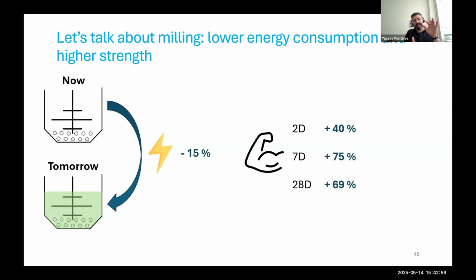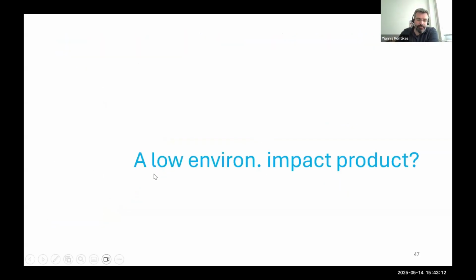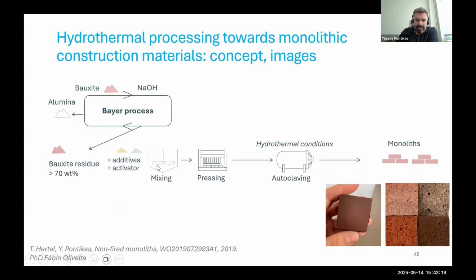So instead of then actually sending the dry powders, you can send the slurry, and you say in that slurry, add your aggregates and 5% cement, cast, because it's still castable, and you have your building materials. And when we speak about environmental performance or low environmental impact and high environmental performance, here is another example.